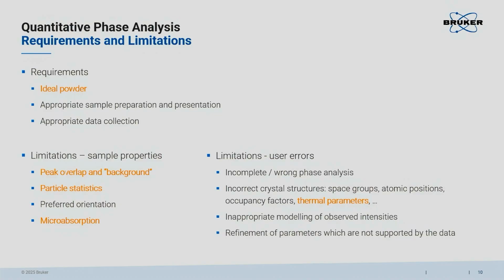I mean, what step size are you using? Typical question at the university in earlier days. Yeah, 0.02 degrees 2 theta. Why? Yeah, because my supervisor told me so. Not uncommon still today. So step size, counting time, 2 theta range to be collected. At my university, in the earlier days, where we still had scintillation counters and where measurement took 1 hour, the 2 theta range had to fit into a 1 hour slot. It didn't matter if the data quality was poor or not, because after 1 hour, the next student wanted to measure. So you should know which step time you use and why, and also for the step size.